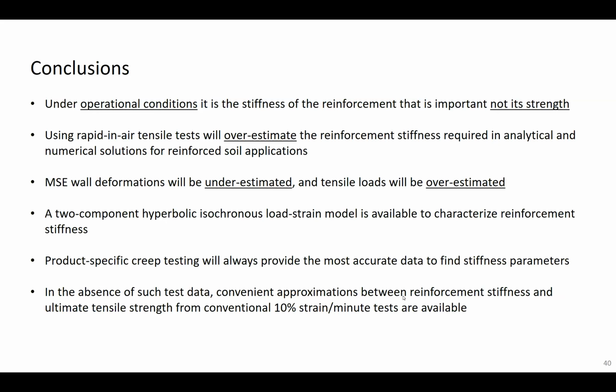From this database, we can appreciate that if you can do product-specific creep testing, you will get a more accurate estimate of the stiffness parameter, and therefore your models, either analytical or numerical, will be more accurate. If you don't have this data, there are some convenient approximations that relate stiffness to the ultimate tensile strength of the material, which is something that we always have from the manufacturers and suppliers.